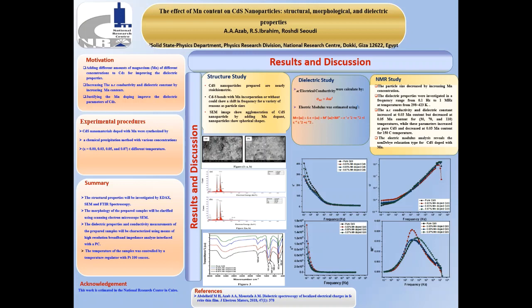From the figures, we can confirm the structure of cadmium sulfide by the EDX technique and find that cadmium sulfide is nearly stoichiometric. We also studied the Fourier transform infrared technique and can confirm that cadmium sulfide is formed by doping manganese in cadmium sulfide. The dielectric properties are improved.